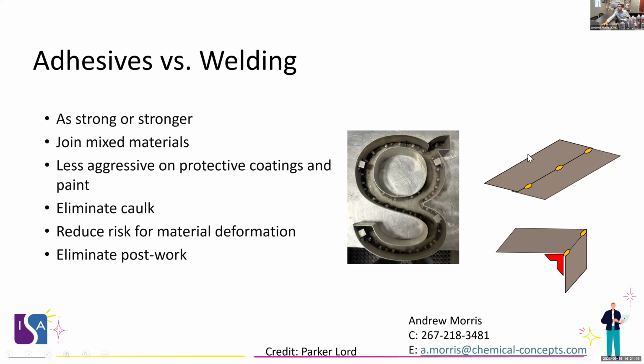So using this example in this picture, you'll see two rectangles with three spot welds. Now compare that with an adhesive joint, same geometry, same pieces, with a continuous bead of adhesive with a 1-inch overlap. A typical strong MMA 10-to-1 acrylic adhesive might be 2,000 to 3,000 psi for aluminum to aluminum. So if you have a 1-inch wide by, let's say, 12-inch long piece, you have 12 square inches of bond times 2,000 psi. Now you're getting into pretty incredible strength. And so if you were to compare that against that spot welded example, we could absolutely meet or exceed the strength of welding. And again, I don't ask you guys to take my word for it.